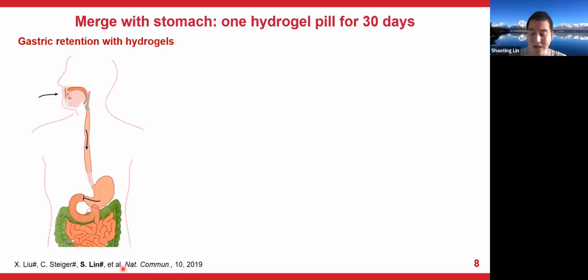So here is the working mechanism. The patient first orally takes one hydrogel pill in the size of 1 centimeter. And once the hydrogel reaches the stomach, it swells rapidly by 60 to 100 times in volume and resides in the stomach. And due to its high fatigue resistance, it can not only sustain the long-term mechanical disruption forces generated by the stomach, but also withstand the strong acidic chemical erosive environment.